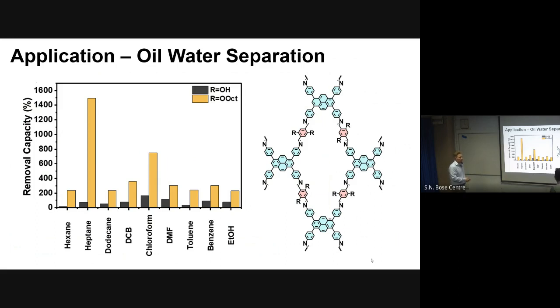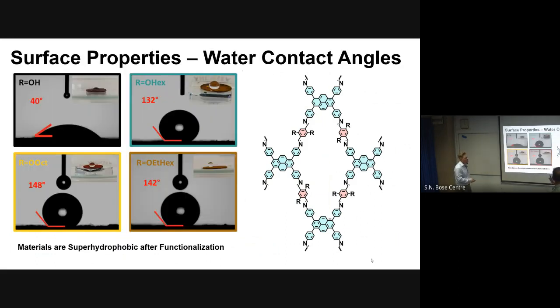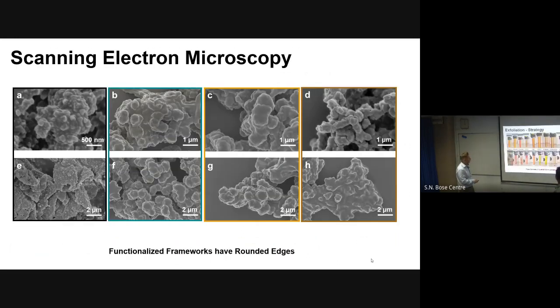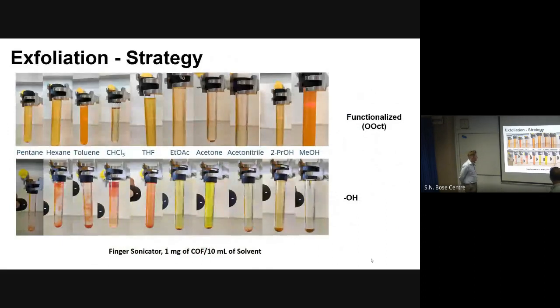And the second question, can you go to the image where you showed the different solvents and the different dispersion in acetone and all those. Okay, this one. If I look at the ether and acetone, I see some color, which is not the color of the bottom one for the hydroxy one. So what is that color? I think it could be remaining linker, because acetone and ether are very good solvents. Maybe taking out some of the unreacted molecules.